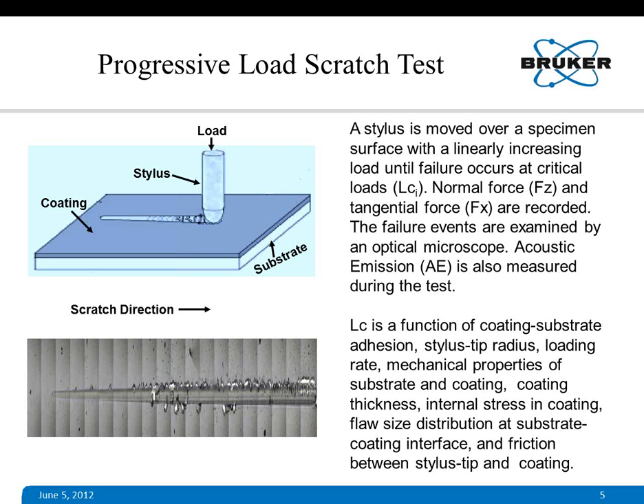The critical load is a function of coating substrate adhesion, stylus tip radius, that is the geometry of the stylus by which you are scratching, loading rate, that is how load is increased with time, mechanical properties of substrate and coating, coating thickness, internal stress in coating, flaw size distribution at the substrate coating interface, and friction between stylus tip and coating.